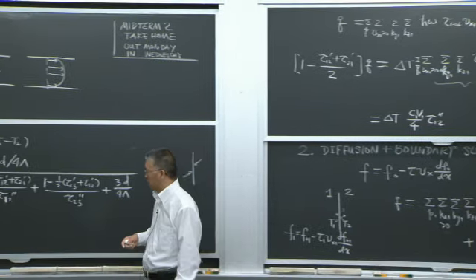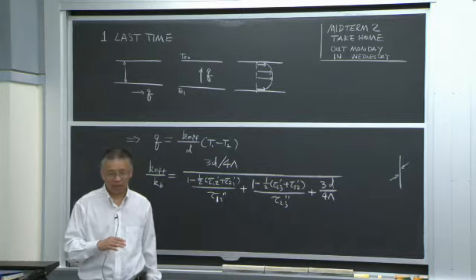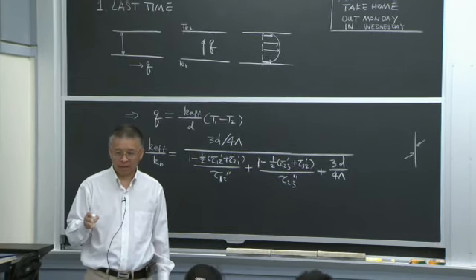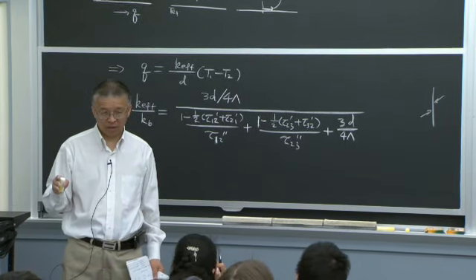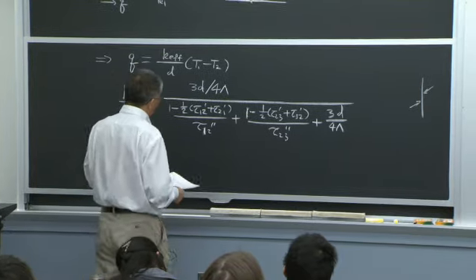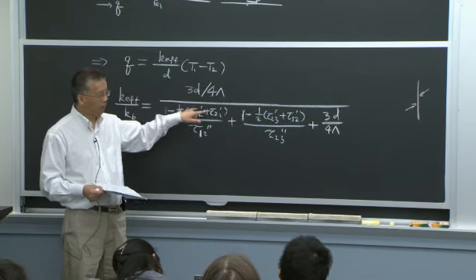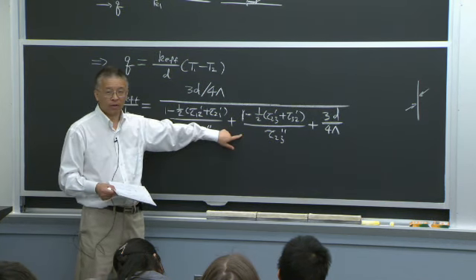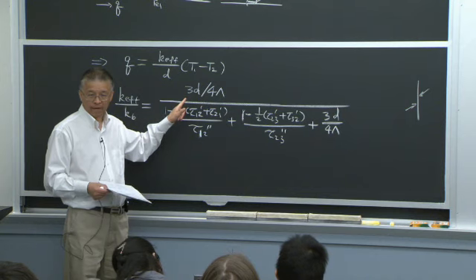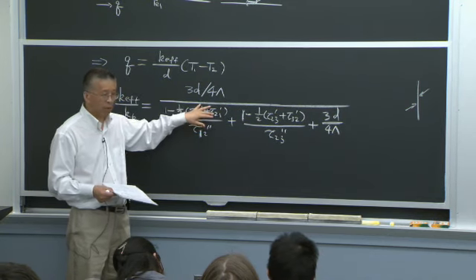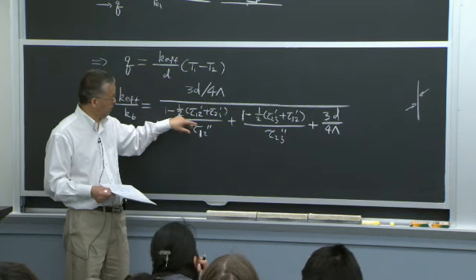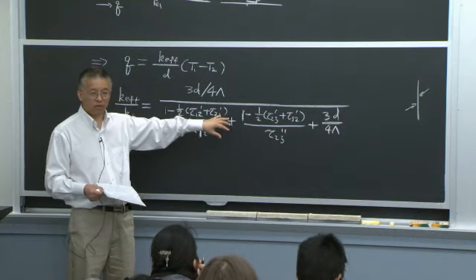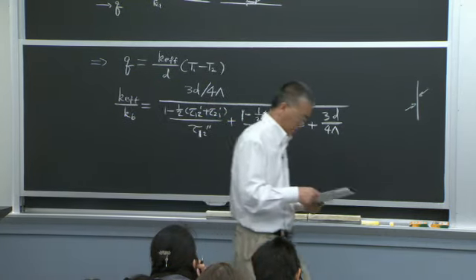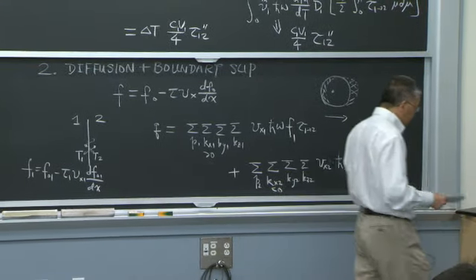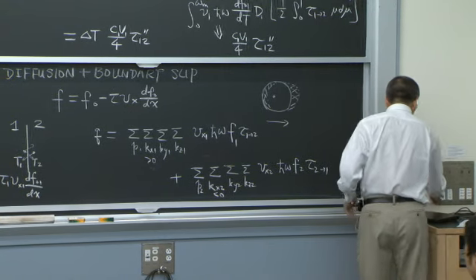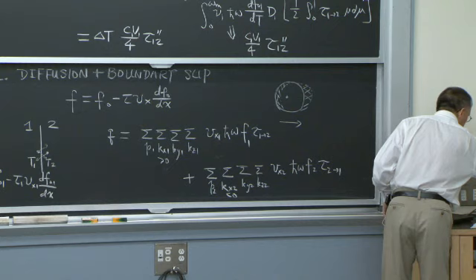So one success of this addition is you look at the limit when there's no interface. When there's no interface, you should get the bulk thermal conductivity, right? And typically, when there's no interface, that means the transmittance equals 1. So this is 1, this is 1, this is 0, this is 0. I go back to 1, right? And in most other work, this term is not included. If you don't use a consistent temperature definition, there will be an additional artificial resistance. So that's a success.